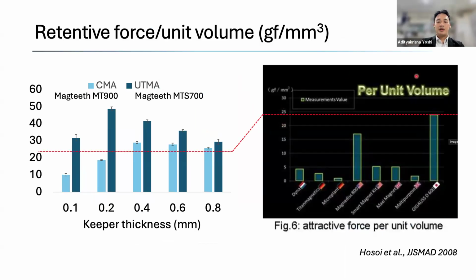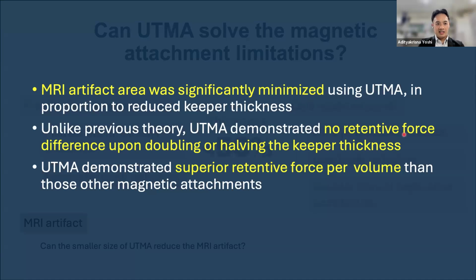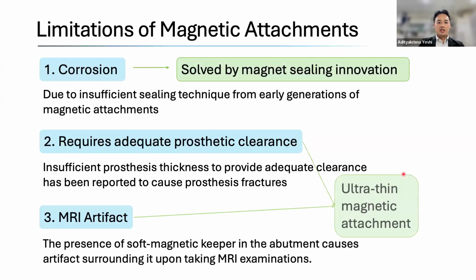And compared with the previous conventional magnetic attachment systems, the retentive force per volume is approximately 2 or 3 times higher. So we concluded from these studies that the MRI artifact area can be significantly minimized using UTMA. Even using the minimized keeper that is available from 0.4 down to 0.2, the retentive force did not reduce significantly and demonstrated superior retentive force per volume. So these 3 problems or limitations of magnetic attachments are expected to be solved with these new innovations in magnetic attachments.